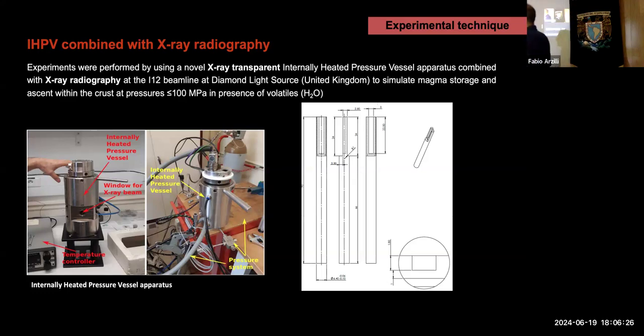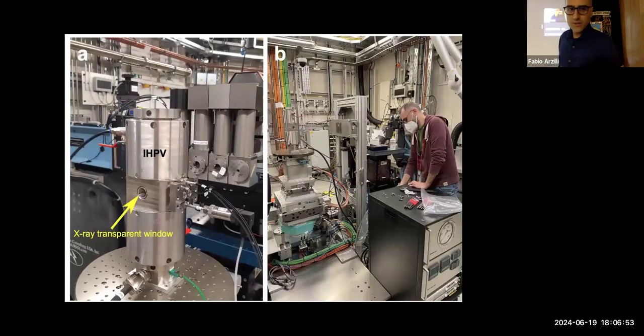And we initially developed a crucible to perform, in this case, radiography and not tomography, because as I said before, tomography needs the sample to rotate. We don't have at the moment a system that is able to rotate internally. So the sample is fixed inside and we can take just fast images through time. So we will have 2D images through time during the compression. And this is the internally heated pressure vessel in the beamline at the Diamond Light Source. This is the camera, this is the system, and this is the pressure control and the temperature controller.